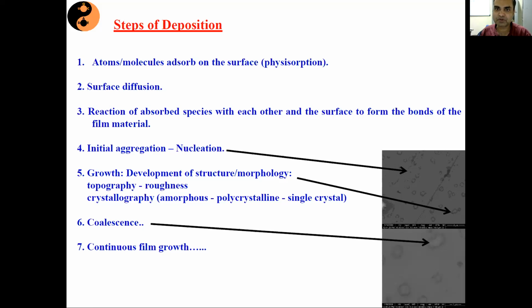Now, here is a point of caution that we all have to appreciate. How long can I move on the substrate surface to find my partner? Is there any timeline? Yes, there is a timeline. If within that timeline I do not find my partner, then I can simply get dissolved back into the atmosphere. I will not stay there for a longer time. This is a very important thing, right? So that means there has to be a proper surface diffusion to take place, so that the evaporant finds its partner to start the nucleation.